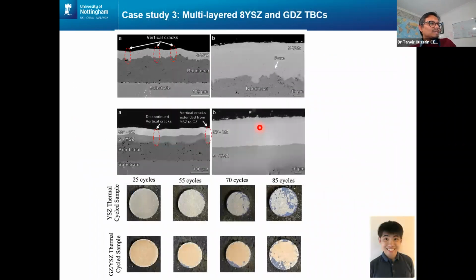Moving on to other systems. If you remember in 2010, when the Icelandic volcano erupted, I can't even pronounce the name properly, Eyjafjallajökull, the entire flight network over Europe came to a grinding halt, because CMAS, or calcium, magnesium, alumina silicate, is highly aggressive to the thermal barrier coating that we have. So the last 10 years of research have gone into coming up with new compositions which can prevent CMAS attack. Here, Leng is a PhD student at the moment. Leng is developing a solution precursor gadolinium zirconate, a very dense coating, over a suspension sprayed YSZ to see how they would perform under thermal cycling and in CMAS conditions.